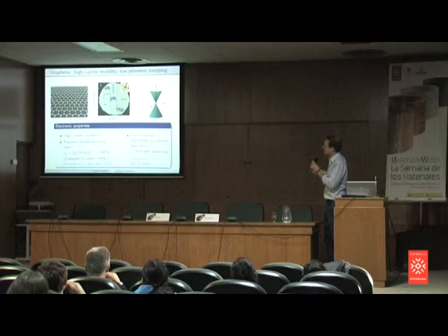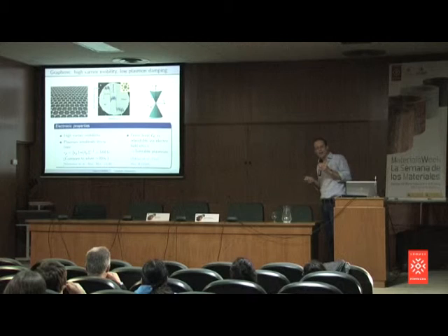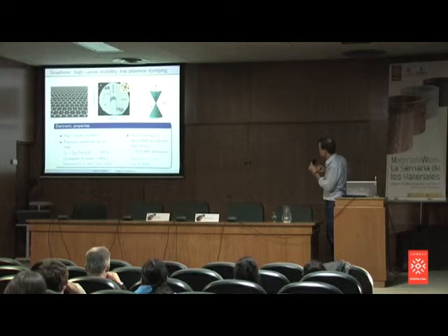Well, one thing which is connected to optics: it absorbs in the visible frequency range, let's say, 2% of light. That's why we can see it. Here is nothing at all. Here is one layer, here is bilayer graphene, and you see it's slightly darker, and that's how they found it, actually. And we have this peculiar linear band structure for the electrons, the Dirac electrons.